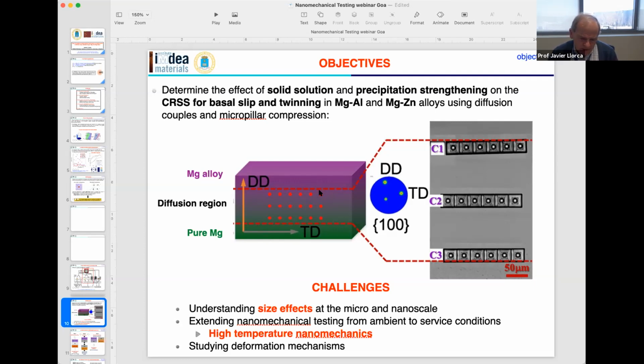And in order to achieve this, there are a number of challenges that you have to solve. One of these is that you have to understand size effects at the micro and nano scale, because you really want to measure properties that are bulk properties. And when you are going to very small scale testing, of the order of microns or below, size effects may be very important. Then we would like to extend this nanomechanical testing technique to ambient and service conditions, so we want to explore high temperature nanomechanics.